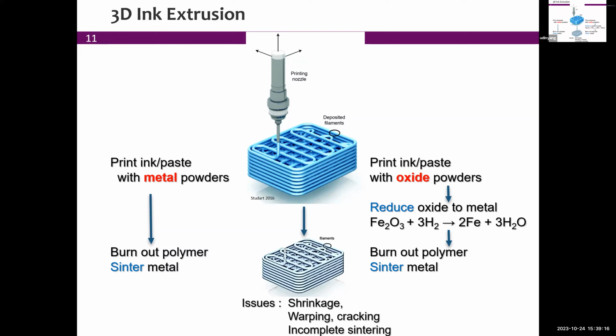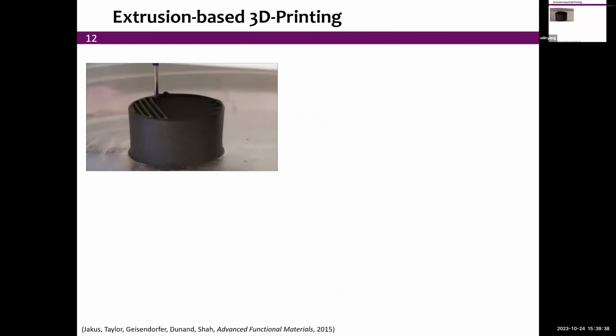You say, well, why go through that? The main reason is that we can use submicron oxide particles, whereas for metal powders, it needs to be quite a bit larger. And using submicron powders allows us to reduce and then have extremely fine nascent metallic powders that will then sinter much, much faster. So that's why we go this way, even though I will describe both cases here.